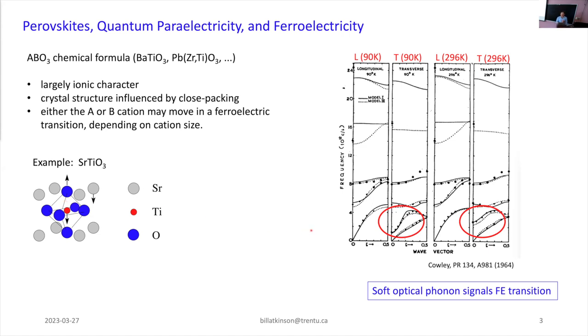And on the right here, what you actually have is a phonon mode. And I've pictured here the eigenvector for that phonon mode. So the eigenvector has an almost rigid oxygen cage that's moving in opposition to the titanium atom. And the strontium atom also moves, but not very much because it's big. Okay? And so this is this soft transverse mode that people talk about.